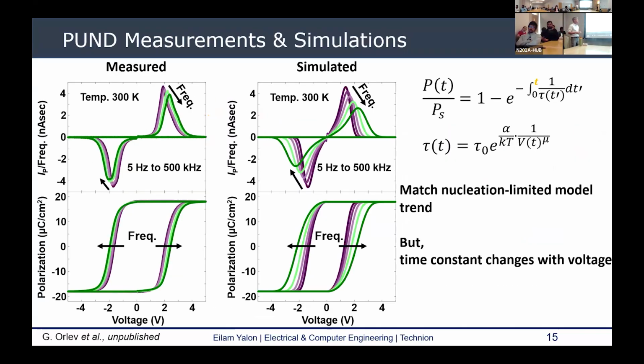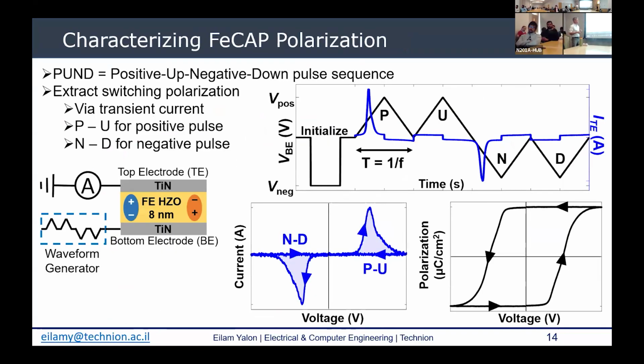But one of the issues with these types of measurements, when we want to study kinetics, is that the switching time depends directly on the voltage, and in this type of measurement, we vary voltage and time together.